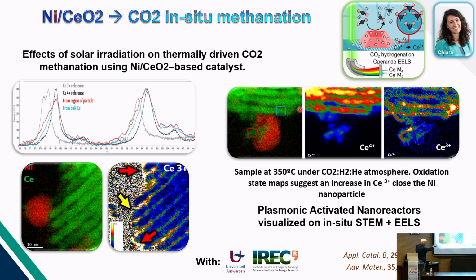With the reduction, you could absorb the CO2 molecule, and then with the spillover of hydrogen, you could create the methane with the CO2 that is already reduced. But in this case, what we could do is doing it directly in the microscope. And the nice thing is that when you were applying hydrogen with the CO2, you could see here by heating,